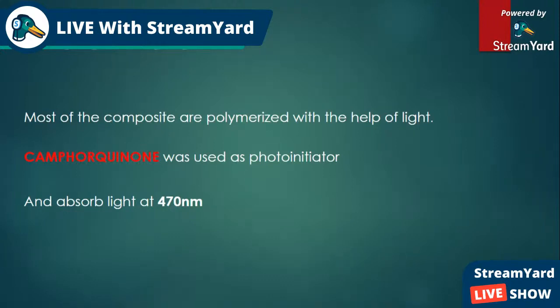Most of the composites that we are using nowadays are polymerized with the help of light. It uses a chemical known as camphorquinone, which is a photo initiator. It activates itself at a wavelength of 470 nanometers. It absorbs light at 470 nanometers and starts the polymerization.